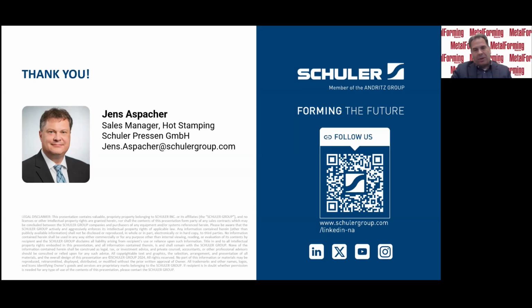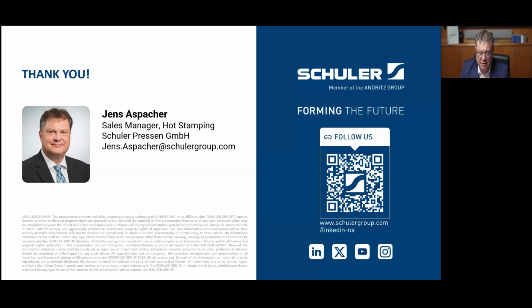Interesting question. Are you considering using this process for steel hot stamping? Yeah, we did some. The basic tests have been done at Imperial College. We did some tests with our hot stamping die with high strength material, which we heated up to about 500 degrees. It was quite good formable, but then we stopped these trials, because we were afraid that we would damage our die, because it's a hot stamping die designed for soft forming material and not for high strength material. And because we needed it for more trials, we didn't want to destroy it.